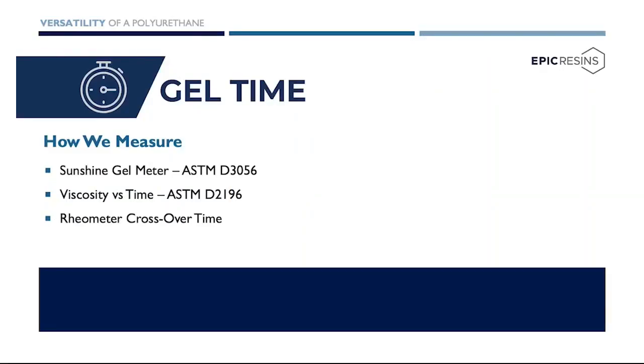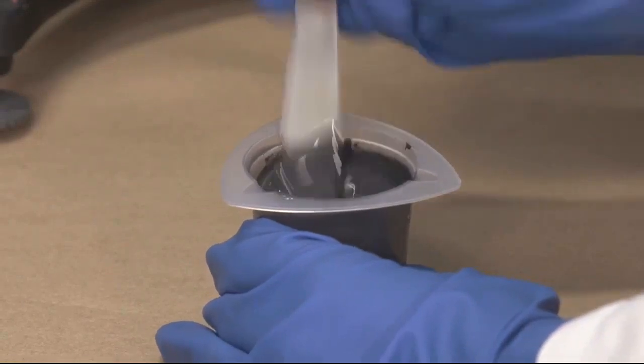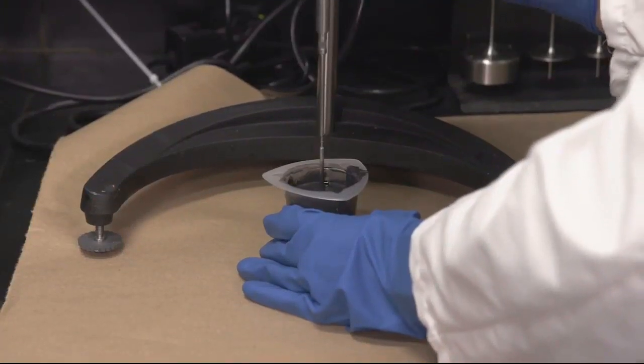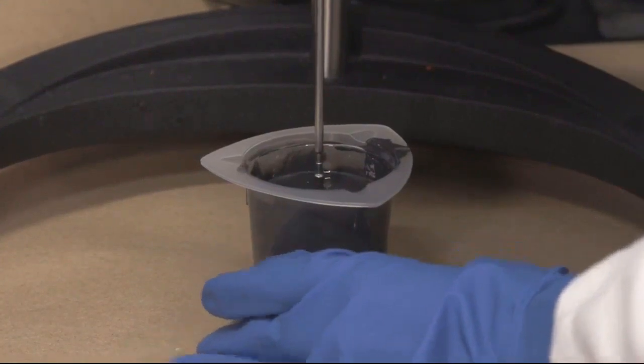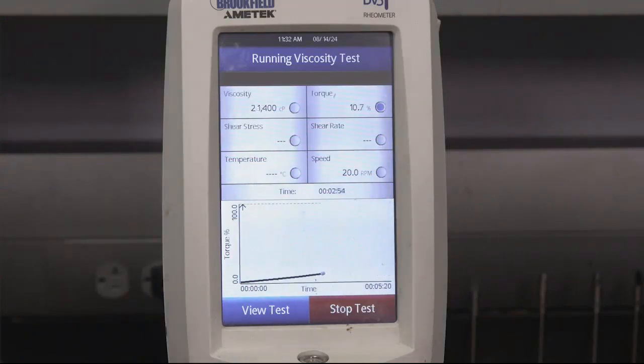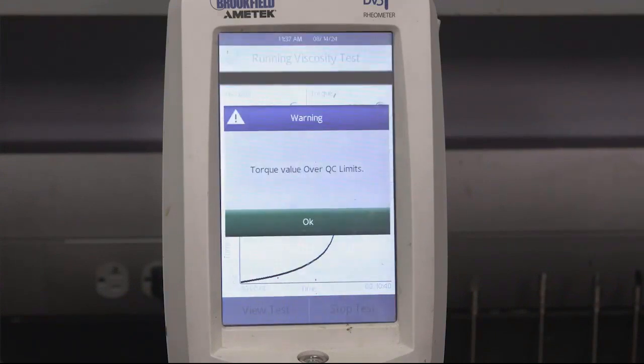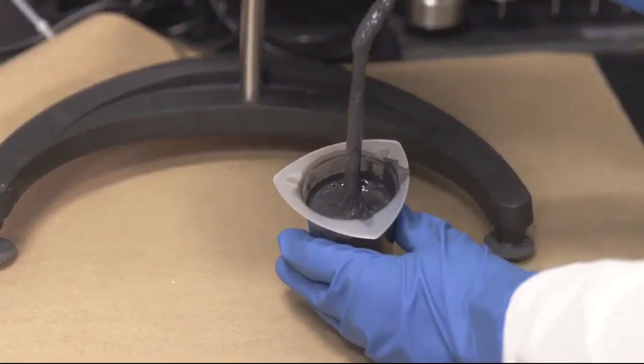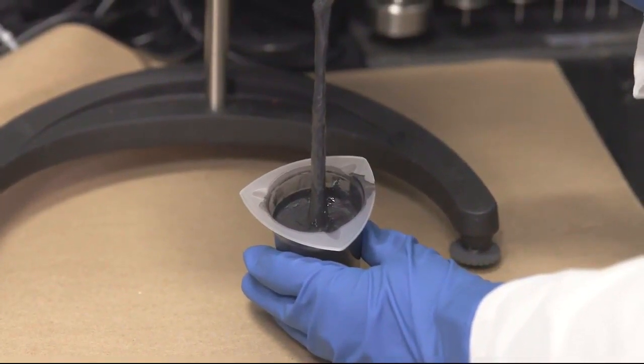The second method is used for systems with a slower transition from a liquid to an elastomer. This method utilizes ASTM D2196, which measures viscosity in centipoise as the polymerization reaction proceeds. Ultimately, this test monitors the viscous nature as the polymerization reaction transitions the material from a liquid to an elastomer. In most cases, gel time is defined by a terminal viscosity that is prescribed based on the application where the material is being used. Typically, this method is used for systems with a gel time of 20 to 40 minutes.